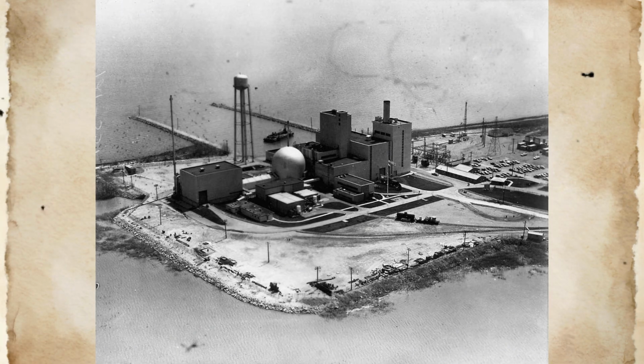restriction. The critical failure mechanism occurred when the loose zircaloy deflector plate came to rest in a position that created substantial blockage of coolant flow to specific fuel assemblies. The fuel assembly inlet nozzles were designed as simple cylindrical openings approximately 4 inches in diameter that directed sodium coolant upward through the fuel pin array within each assembly. When the deflector plate, measuring 16 by 8 inches, lodged against or partially covered these inlet nozzles, it reduced the effective flow area available for coolant circulation through the affected assemblies while maintaining normal flow rates through adjacent unblocked assemblies.